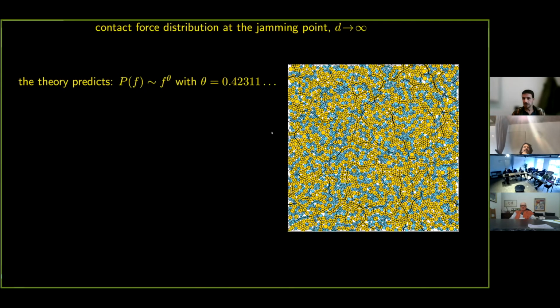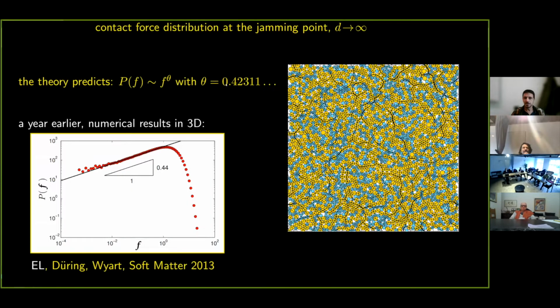All right, so going back to the results, the theory predicts that the distribution of contact forces, as I mentioned before, at the jam state goes like f to the theta, with a non-trivial theta that they could calculate from the theory using numerical solutions of the equations. Actually, a year before this prediction came out, which was in 2014, together with collaborators, I calculated the distribution of contact forces in 3D packings of hard spheres. And I found an exponent of 0.44, which is reasonably close to the prediction for the infinite dimension jam states. And we were very happy to see that there is a theoretical explanation for the exponent that we measured. Measuring this exponent is not trivial because there are essentially two classes of contacts that carry low forces.